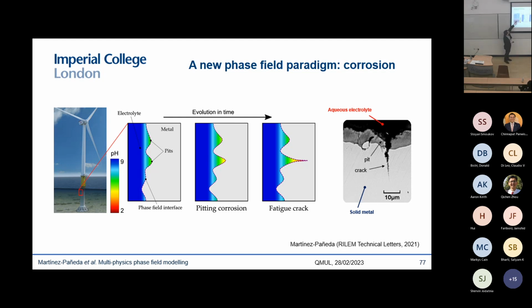If you think, for example, of the corrosion fatigue of offshore wind turbines, which is their limiting design criterion, the process is something like this. You nucleate some pits, then those pits grow, and eventually they transform into fatigue cracks that grow all the way until the failure of the monopile. How these pits grow, how fast they grow, and when they turn into cracks is very sensitive to their shape and to the deformation and chemical problems. At the same time, the deformation and chemical problems are very sensitive to the shape of the pit. If a pit is very sharp, of course, you have a higher stress concentration, and also the local chemistry is going to be much different from the bulk chemistry. So everything is very strongly coupled.